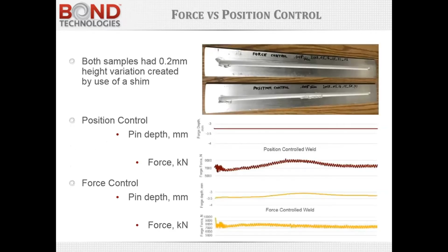One of the key aspects of friction stir welding is the use of forge force. You can do this in position control. In other words, plunging into the material, getting shoulder engagement, and traversing along the joint with a constant position. But if there's any variation in the material thickness or the tooling, it can result in a variation in the engagement of the shoulder. This will affect the weld process. Therefore, the most common method of doing friction stir welding is to use force control, whereby the force is measured and controlled through closed loop control system in order to maintain a constant force, which causes the position to vary.